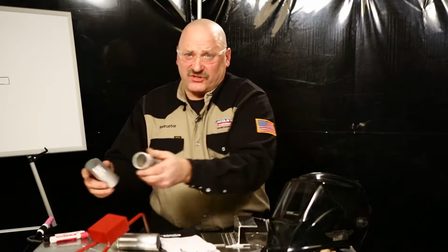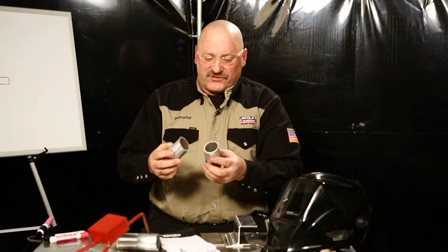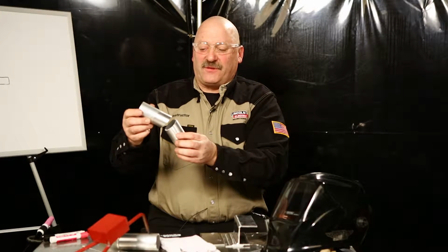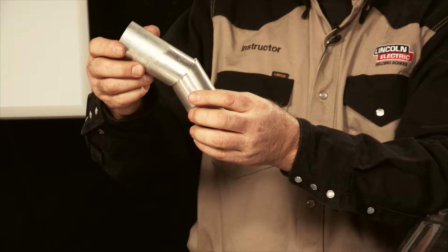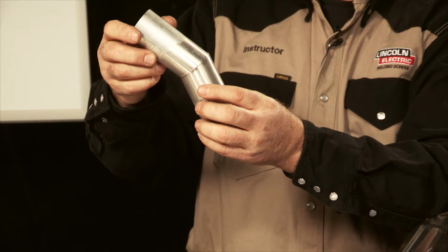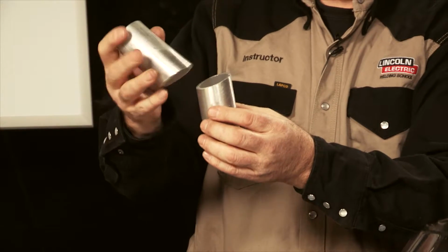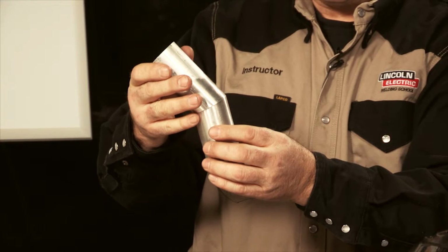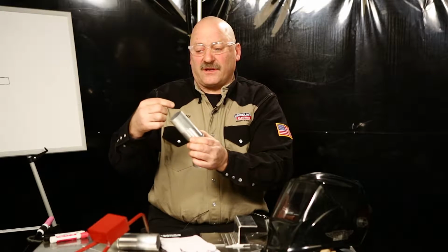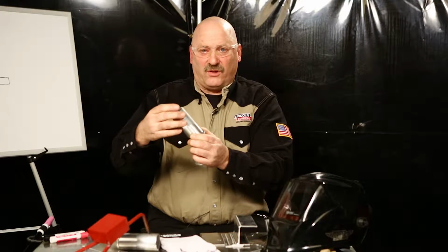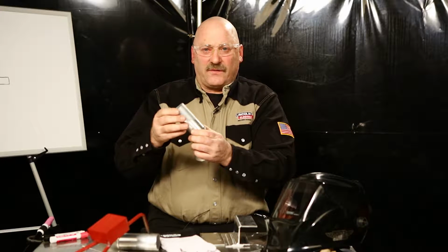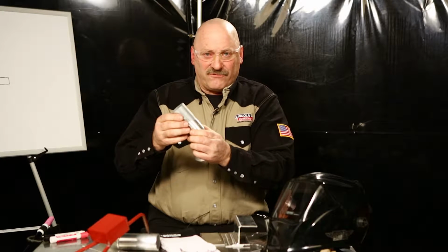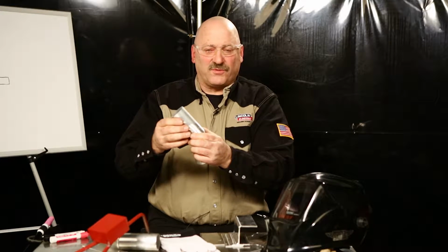Sometimes when we fabricate structural aluminum, which is often 6 series, we might cut miters and fit pieces together like this. Well, that's a butt joint. That's a square butt joint. And welders know that they can penetrate all the way through that butt joint. But when they do that, you're going to get a lot of base metal mixed into that weld. And they don't make 6 series filler metal for a reason, because all the welds would crack. It is prone to solidification cracking.